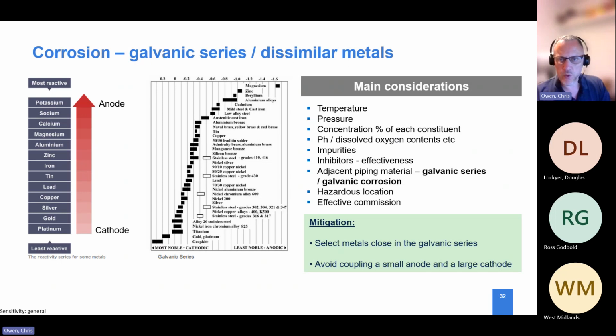But we saw a lot of people switch across to stainless steel with the belief that stainless steel didn't corrode and they could have these thin wall tubes. The problem is that stainless steel does corrode, but more importantly, it's more cathodic in what we call the galvanic series. Stainless steel can be used in process pipework, catering pipework, where the rest of the system is also stainless steel. When you see stainless steel being used in building services, normally there are other materials such as carbon steel or copper in those pipework systems. So we call them mixed metal hybrid systems.